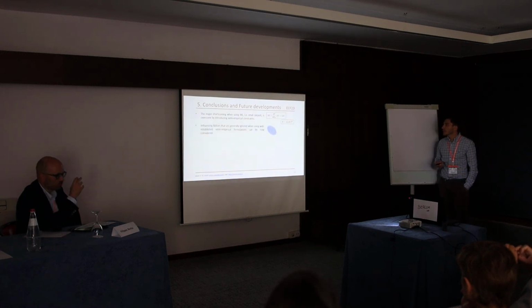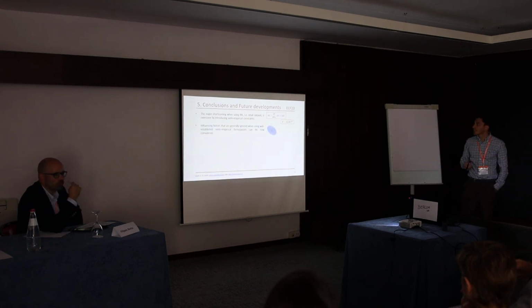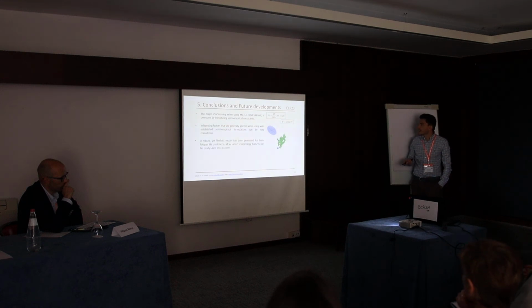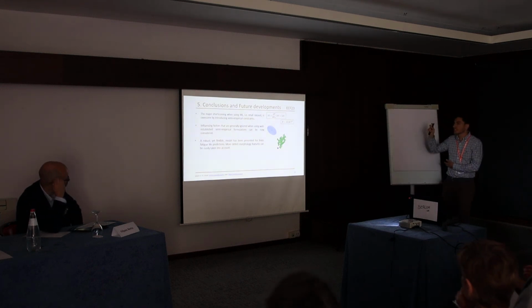So I go to the conclusions. We have shown how a physics-informed machine learning technique can overcome some limitations of purely machine learning-based approaches. We have proposed a semi-empirical model, and we can also account for several other influencing factors that cannot be accounted for in linear elastic fracture mechanics. And it is robust and flexible, so we can also add more data. I just showed you how to employ the sphericity and the equivalent diameter, but we can have more morphology features.